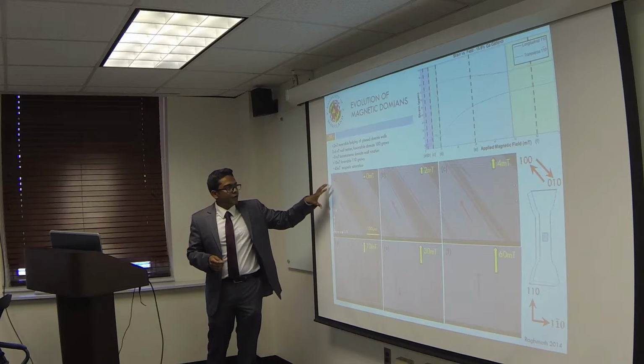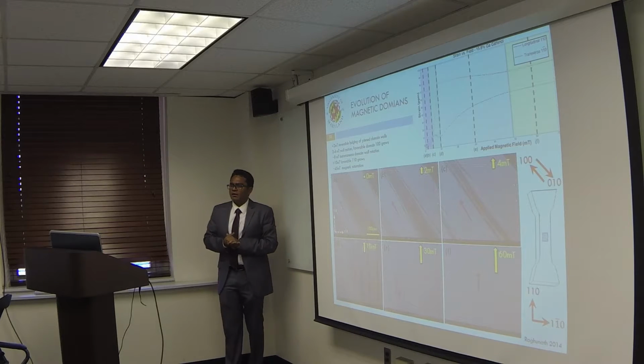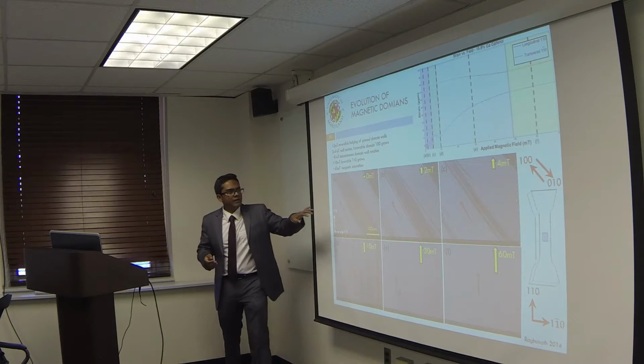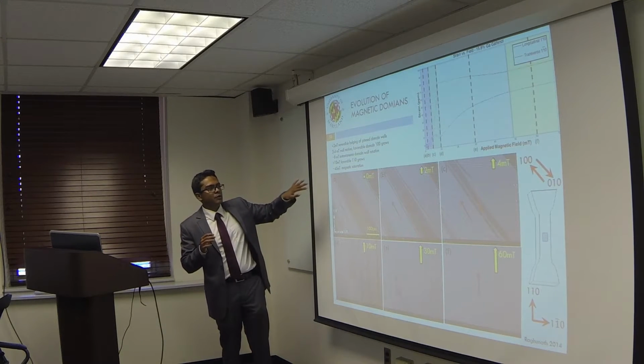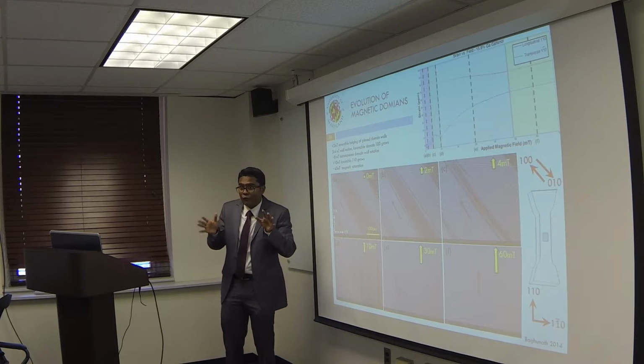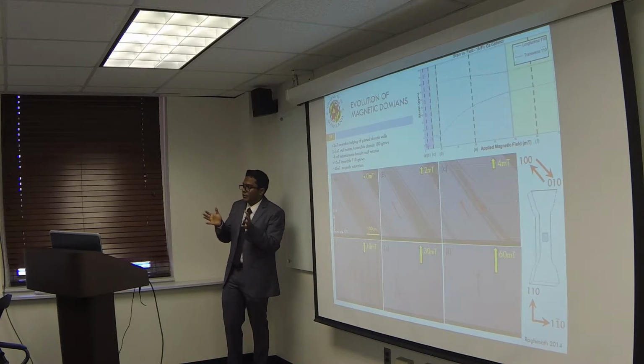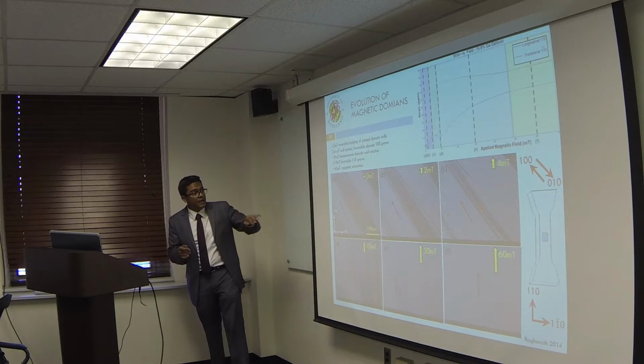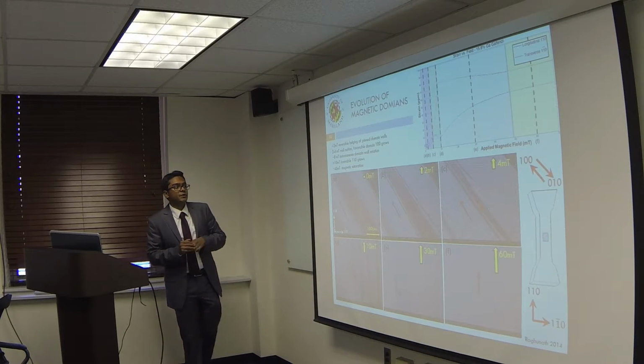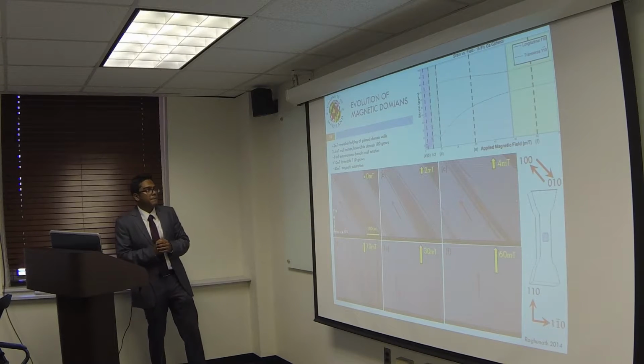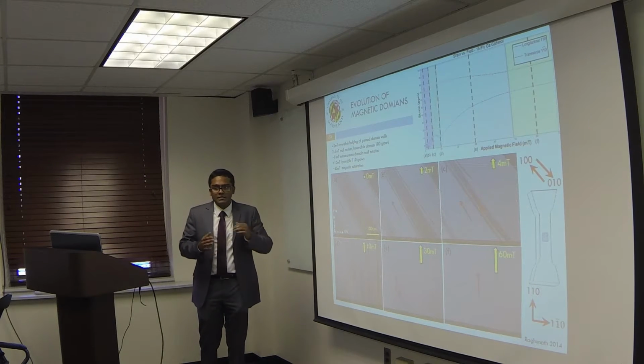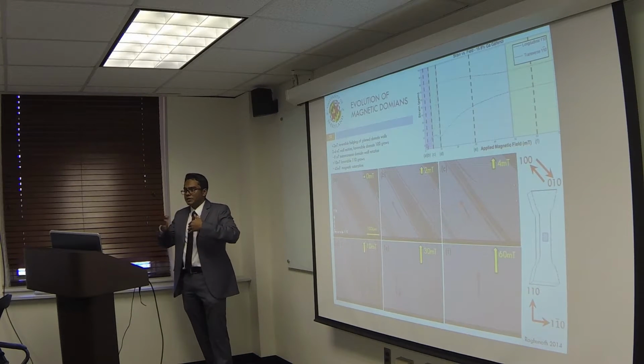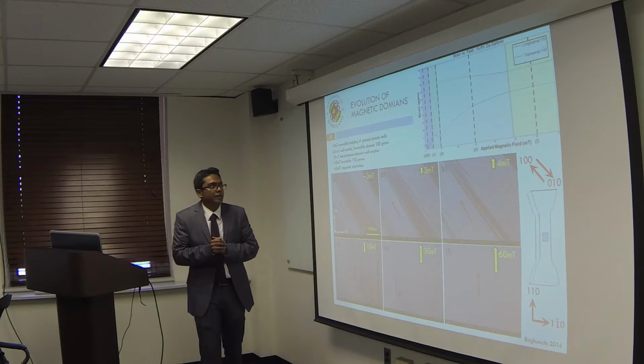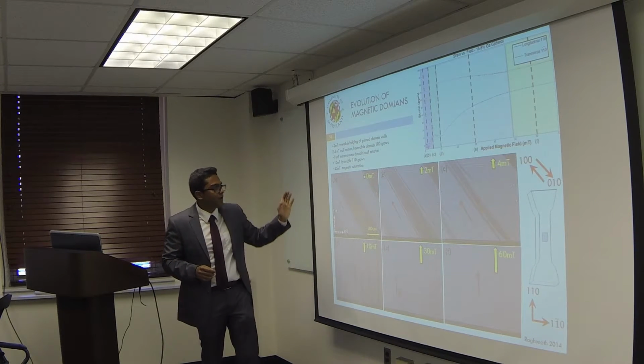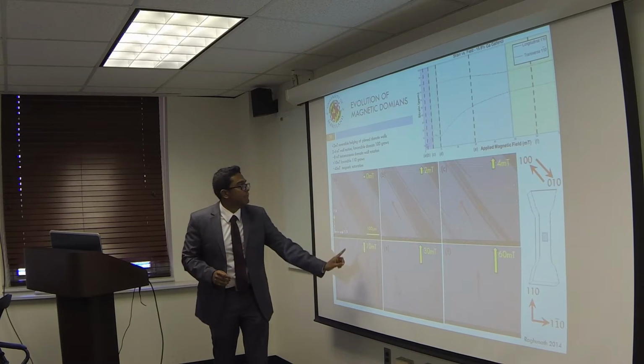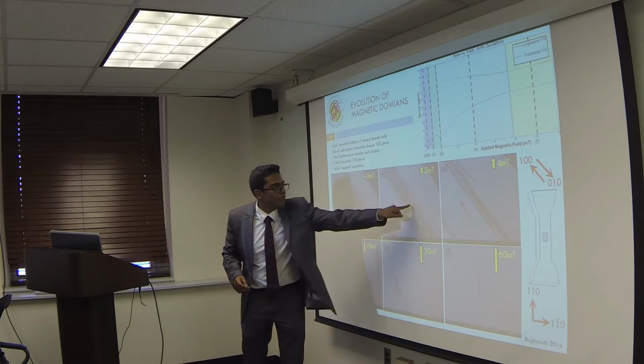So at 0 field, there seems to be some sort of a uniaxial anisotropy. Instead of having the domains oriented along all 4 of the favored 100 directions, we just have the domains oriented along a particular 100 direction. For small applied fields, the domain walls are pinned; the domains grow, bulge and go back to where they were. And for more magnetic field, the favorable domain grows. So in this case, I'm applying a field going that way. So this is not favored, and this is favored.